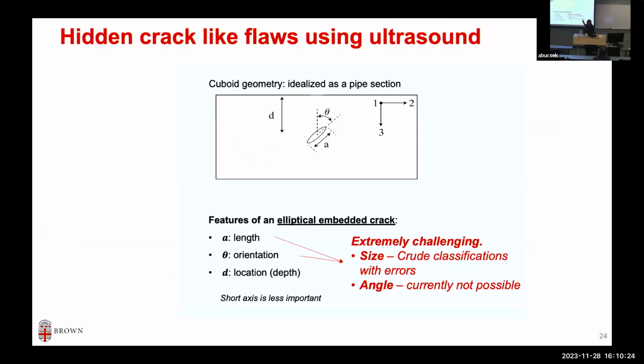The first problem I picked was a very well established, known problem in industry. If you have an embedded crack, anywhere you go, things fail because there's a crack that you cannot detect. Once the crack reaches a critical crack size, the load will cause a fast fracture and catastrophic failure, right? So part of this was to develop a better fracture model, but the input of the fracture model is the crack length and the load. Load you know better, but the crack, if you cannot see inside the structure, you don't know what it is. How do you know that you're predicting the right life?